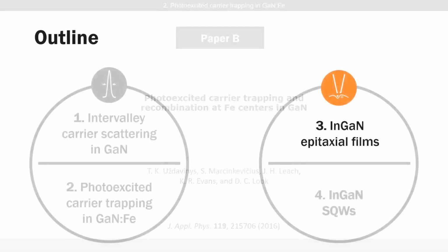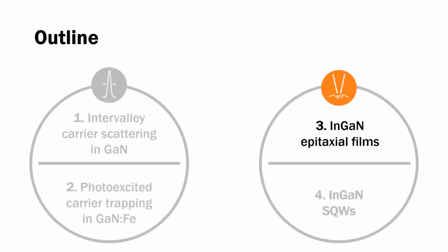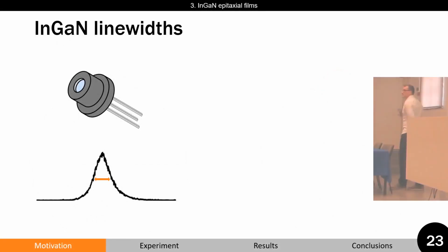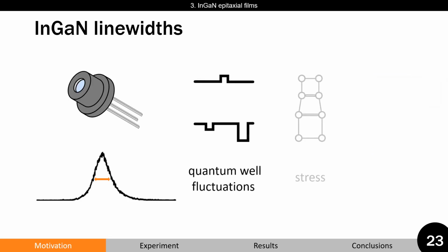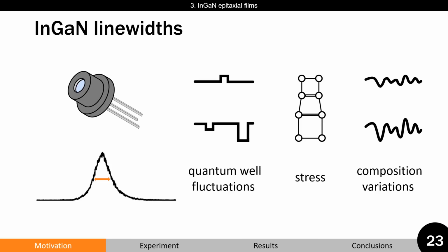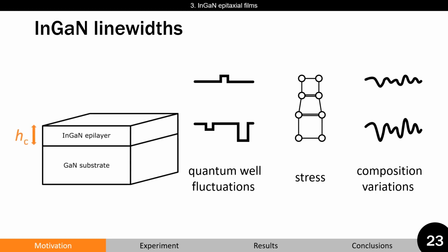This brings us to the second part of my presentation, spatially resolved optical properties, and I will begin with indium gallium nitride epitaxial films. For lasers to have high modal gain and low lasing threshold, spontaneous emission needs to be spectrally narrow and spatially uniform. In the case of indium gallium nitride, there are three mechanisms responsible for photoluminescence broadening. In order to study only one of those mechanisms, we investigated indium gallium nitride epitaxial films.